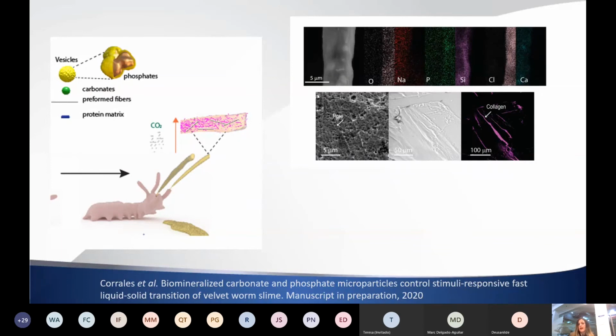All the phosphates and carbonates are released, and the slime is acidic. If you have acid with carbonate, you can even form CO2 to help form a foam. You see here the pores. This is the material already expelled. You see a porous material formed. Also, we see that we don't find any more sodium, phosphate, or any other metal in particles, if not all over the material.